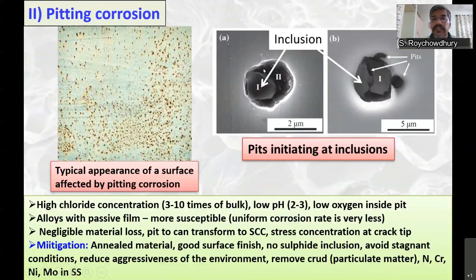The environment within the pit is very different from the bulk environment. It can have a very high concentration of chlorides, 3 to 10 times the bulk concentration. The pH is very low, highly acidic, 2 to 3, and totally deaerated. So you can imagine the bulk environment is very different from the environment within the pit. If you have a highly flowing condition, then what happens? The environment within the pit gets refreshed very easily. In that case, the pit will not grow. So pit growth is favored only in stagnant conditions.